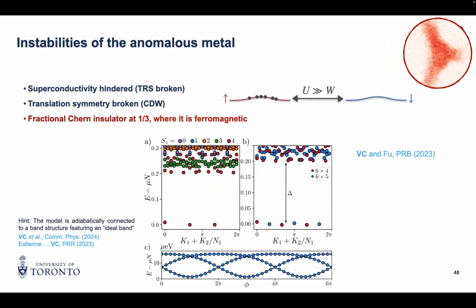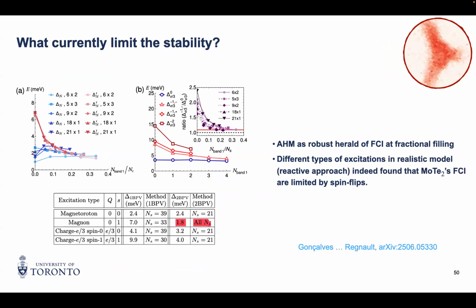But the problem with that material is that what limits the Tc in this material is that you need to fully polarize the system to see the channel number. Otherwise, if you had spin up and spin down, you would have by time reversal invariance the contribution C = 1 from the spin up and C = -1 from the spin down. Overall, no topology or no clear edge modes. And to polarize the system, you need to go below 10 Kelvin, typically, I think it's 13 in the experiment. But what really limits the stability of your state is this magnon gap, so the spin flip energy. And it's not the true gap that I was showing above, which is about 2.4 here.